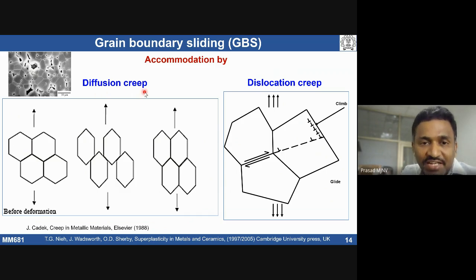In one case we can see diffusion creep accommodation, in the other a dislocation creep accommodation. So when there is grain boundary sliding, apart from it we may also see dislocation climb activity or diffusion creep activity, that minimizes the cavity formation in the material. If this grain boundary sliding is accommodated by diffusion creep, that mechanism is called Lifshitz sliding. If grain boundary sliding is accommodated by dislocation creep, so that we have almost no cavity formation, that mechanism is called Rachinger sliding. Diffusion creep always leads to a shape change in the grain. Dislocation creep accommodation leads to almost negligible shape change of the grain during superplastic deformation.